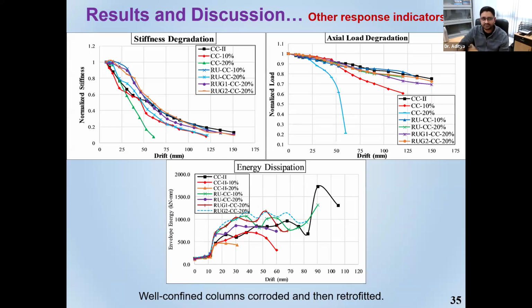If a structure has a higher amount of seismic stiffness degradation, it is supposed to have larger drift ratios, and therefore it may be a problem with respect to collapse or other types of structural distress such as cracking and others. So stiffness degradation is also not expected in the columns, and corrosion actually affects the stiffness and the axial load capacities of your column significantly.